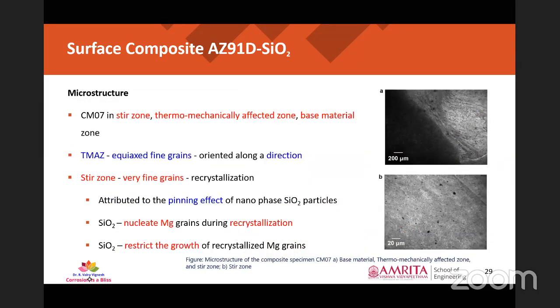So in the specimen CM07, we could see the stir zone, thermomechanically affected zone, and the base material zone. The TMAZ has equiaxed grains, and very fine grains. That is all because of recrystallization phenomenon. So this recrystallization is attributed to the pinning effect of nanophase silica particles. Why? Because these nanophase silica particles nucleated magnesium grains during recrystallization phenomenon, and it also restricted the growth of recrystallized magnesium grains as indicated in the existing literature.